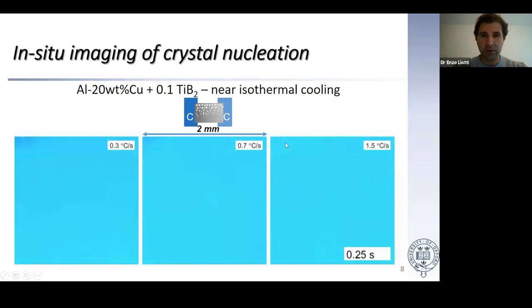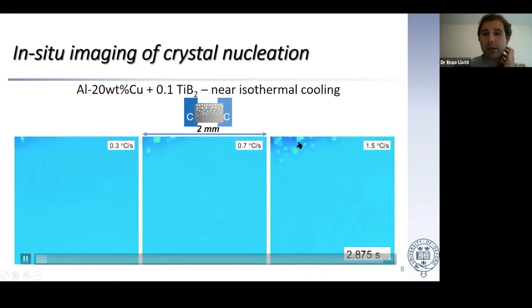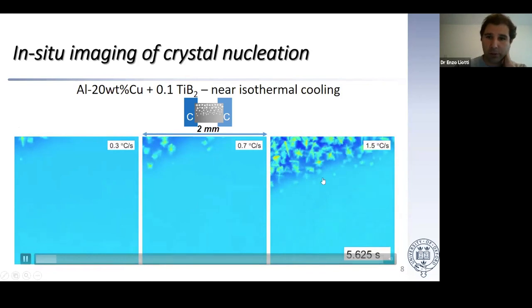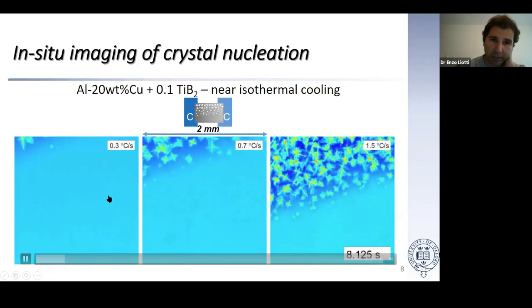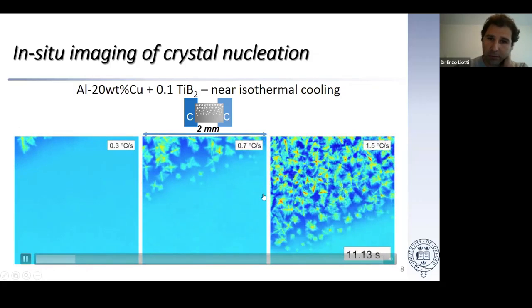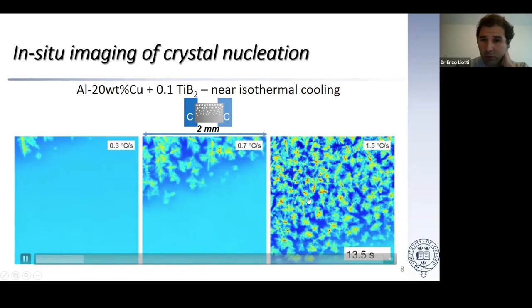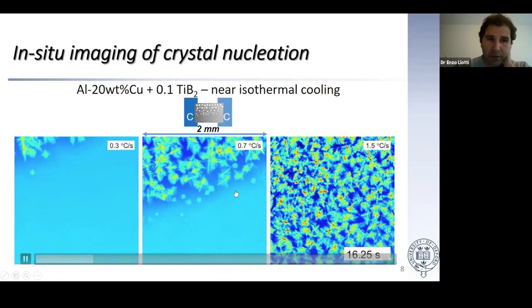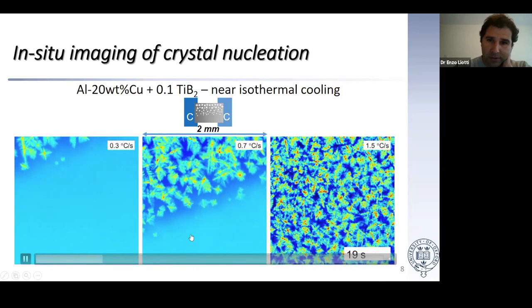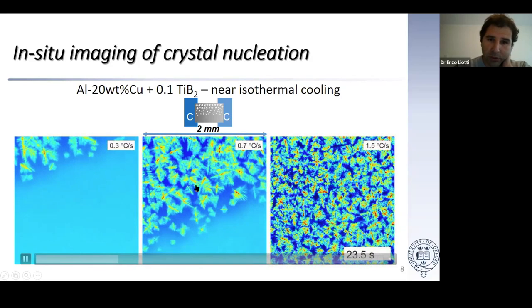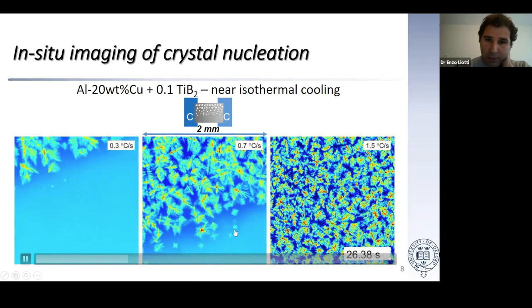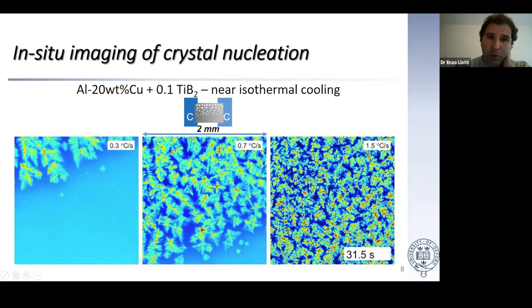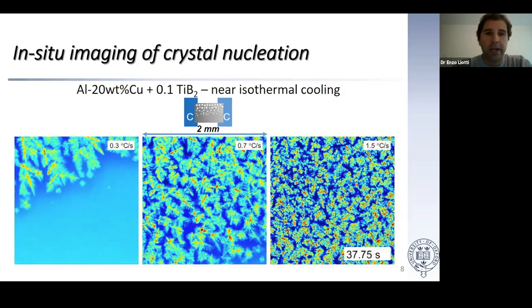If I start the video, you will see the grains forming. These are small aluminum dendrites forming from the liquid, which is initially liquid. Of course, because we are cooling at 3 different cooling rates, the evolution of the solid fraction is different. However, even by eye, you can qualitatively see that the grain size on the right is much smaller than the one on the left. That's for 2 reasons: because of growth, and because nucleation is more copious, right? This is a known effect of cooling faster. Normally you obtain a much finer microstructure because you enhance nucleation.